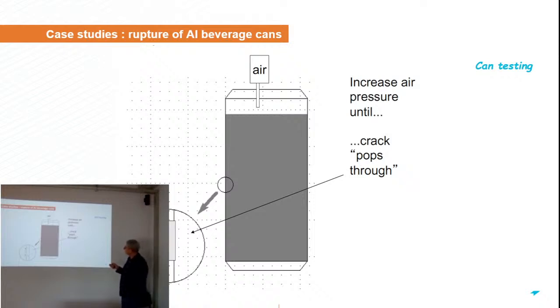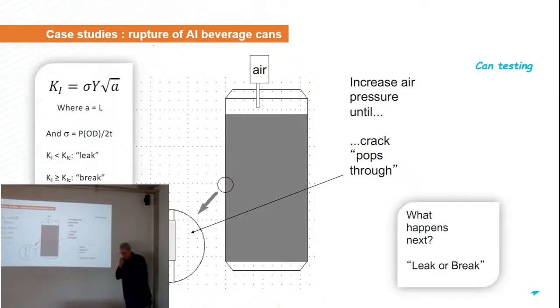So what we do here, we increase the pressure in the can, in the reservoir, and try to find when the crack propagates through. So here we have to consider what we call the stress intensity factor. When you apply stress on a material containing a defect with this size A, you will get a stress intensity factor, which is expressed here as the applied stress times a geometrical constant and the square root of the size of the flaw.